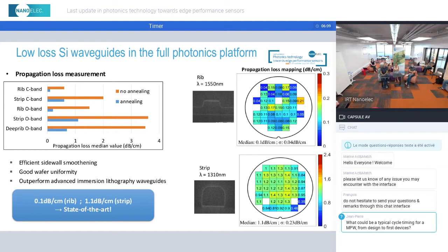On the right side of the slide, you have some mapping of the propagation loss, a measurement at the wafer scale. You can see that the value that I give here, for example 0.1 dB per centimeter for rib waveguide, is the median value over the wafer. So it's not the lowest value, it's the median value. And the standard deviation over the wafer is very good too, with, for example, here 0.04 dB per centimeter for rib waveguide. On the bottom side, it's for strip waveguide, so it's very uniform too.